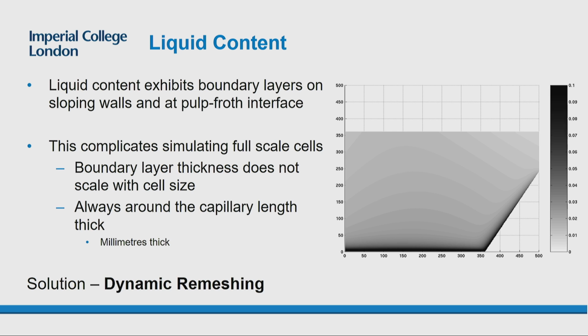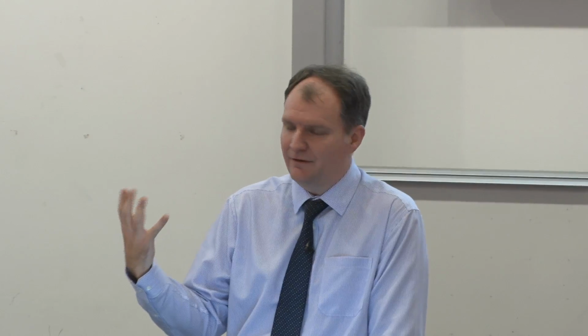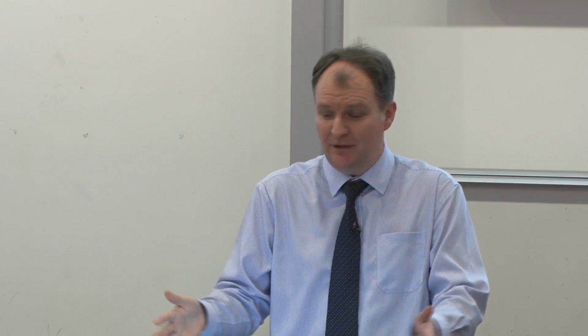In fact, the main thing which changes the liquid content over most of the froth is changes in the bubble size. But near the bottom, so near where the froth and the liquid are meeting, there's a very rapid change in liquid content. And there's also rapid liquid changes in any walls that slope outwards. So you can see another boundary layer against the right-hand wall. And the problem with these boundary layers is they don't change size with the size of the equipment. They're of the capillary length scale thick, whether your equipment is a lab scale piece of equipment, which is what I'm simulating there, or an industrial piece of equipment where you've got half-meter deep froths.